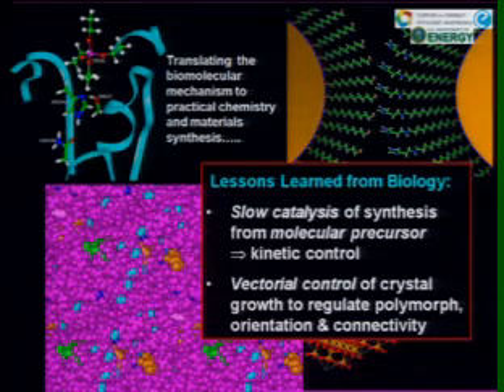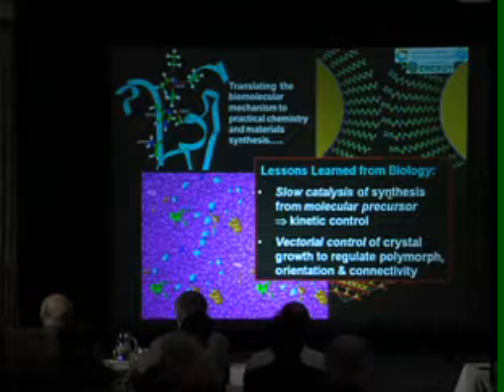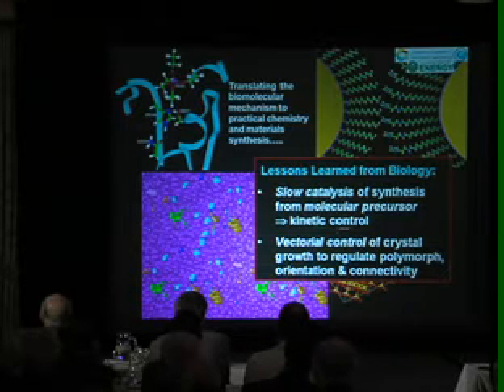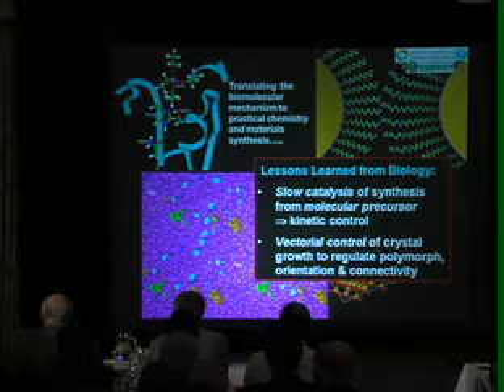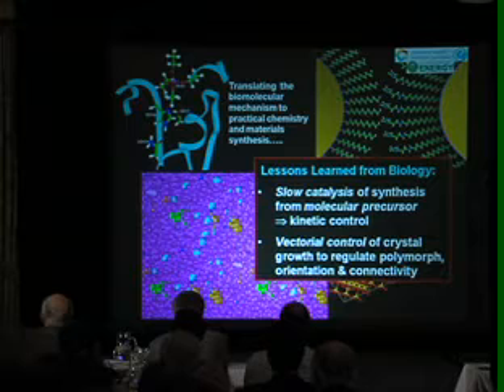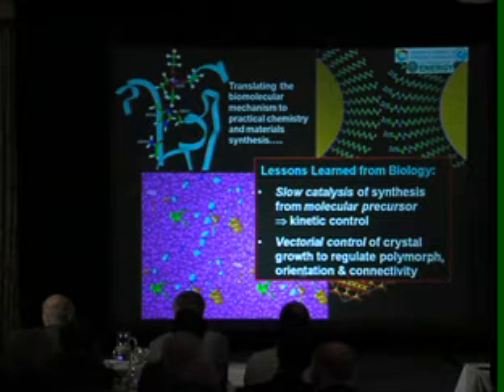First, this enzyme actually works very slowly in the catalysis of synthesis of the silica from molecular precursors, providing an unusual kinetic control of the synthesis, bleeding in essentially the reactants as they begin to assemble, so that the weak cooperative interactions with the template, the protein surface, can control the emergent structures of the nanocrystals, providing a kind of vectorial control of crystal growth, regulating the polymorph, that's the kind of crystal, its atomic orientation and connectivity.